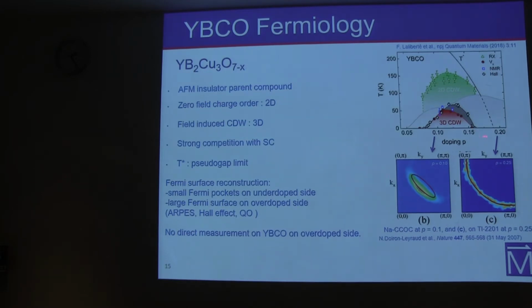So this is for the phase diagram of YBCO, and now for the current picture of the Fermi surface of YBCO. Right now, for the underdoped side, it's believed that there are small Fermi pockets, and as you go from the underdoped to the overdoped side, you develop a large Fermi surface. That was observed somehow with ARPES. But the problem is that you cannot produce samples that are overdoped. The maximum doping that you can get is actually here, optimal doping.